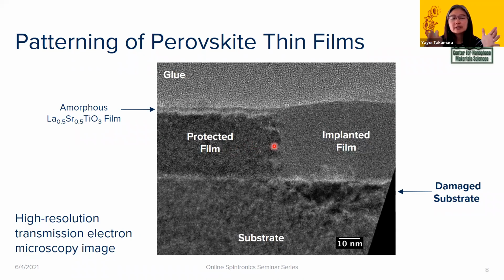And especially since we see that the magnetocrystalline anisotropy is different at the edge compared to the center, right? So we're also wondering if they're all structurally related to each other, because again, it's this few hundred nanometer length scale for both the edge effect and the loss of the magnetocrystalline anisotropy. So one thing is to try to do some very detailed structural measurement of these implanted samples to see if we can see those minute differences in structure.